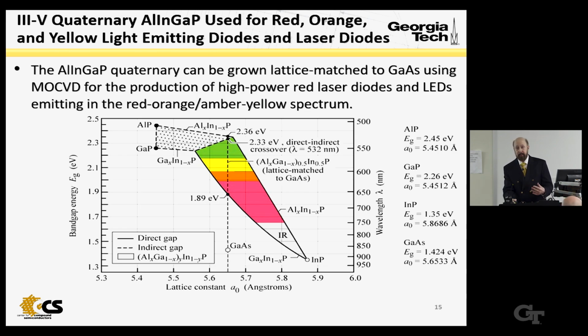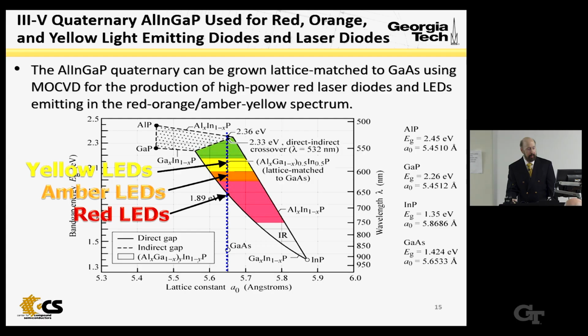But obviously we need a better emitter than gallium arsenide phosphide and heterojunction systems, so people have moved to the quaternary aluminum indium gallium phosphide for red, orange, and yellow light emitting diodes and laser diodes. This plot many of you are familiar with is the energy band gap on the y-axis versus lattice constant of the crystalline structure. In this case, it's cubic or zinc blende on the x-axis. And if you look at the gallium arsenide lattice parameter and its projection up into the quaternary space, you can see we can make very nice red LEDs, amber LEDs, yellow LEDs, but sadly we can't make good green LEDs because it's too close to the direct-indirect band gap crossover.